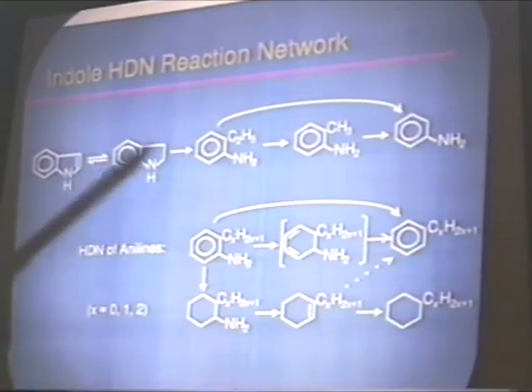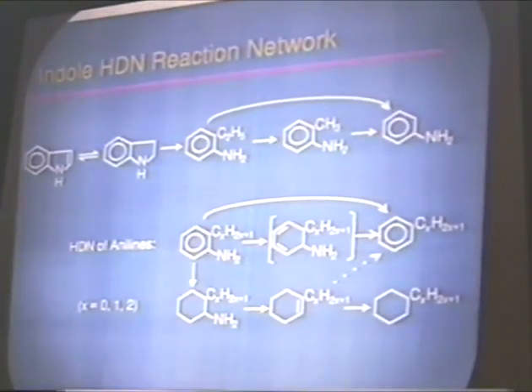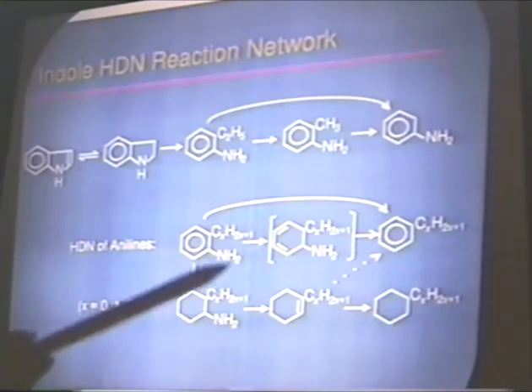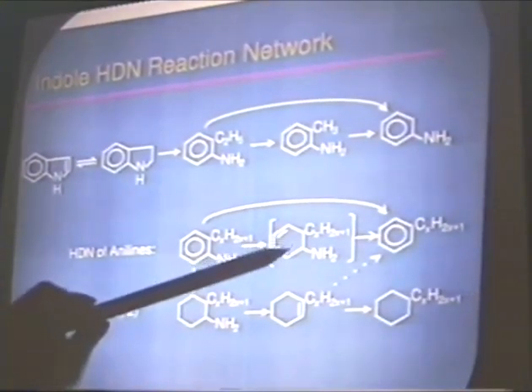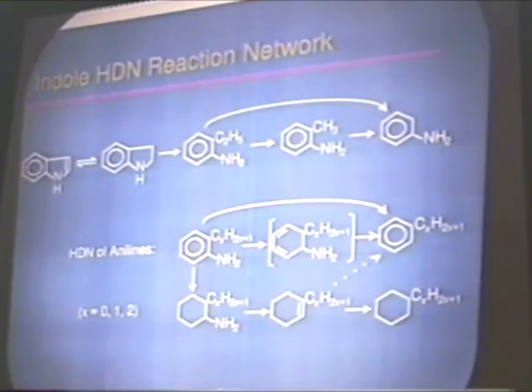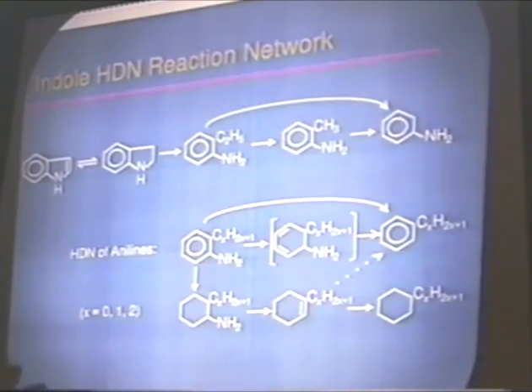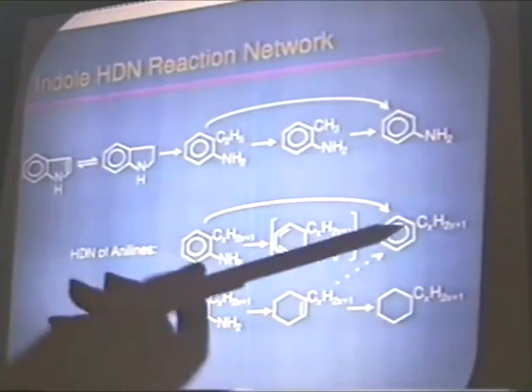ortho-ethyl aniline. And then after the aniline formation, there are different dealkylation steps because we are seeing different anilines in the product stream. And we are suspecting that after the aniline formation, the denitrogenation, again, is going through multiple steps. There's either a complete hydrogenation or possibly a partial hydrogenation, as is seen here, followed by a beta substitution, giving us this nitrogen-free compound, either unsaturated or completely saturated.